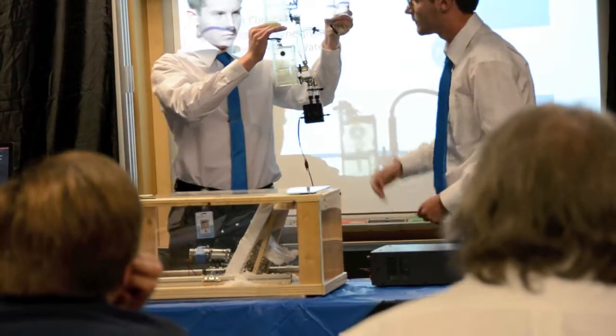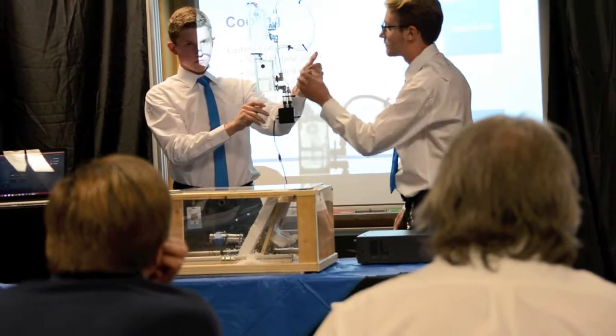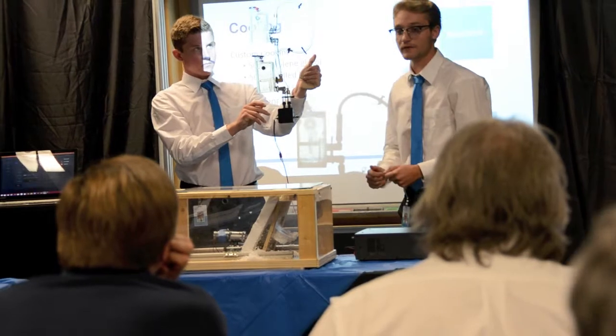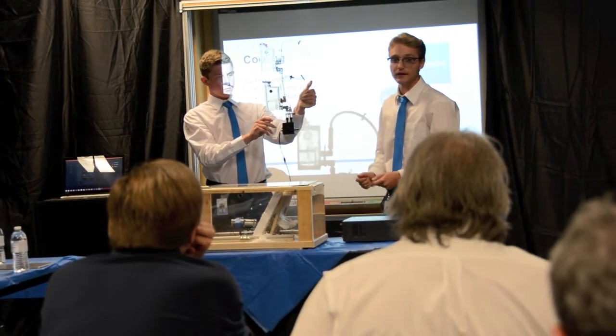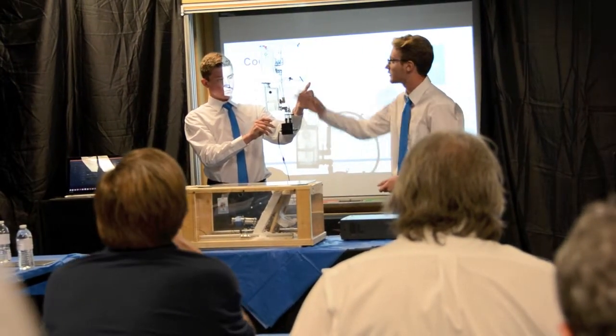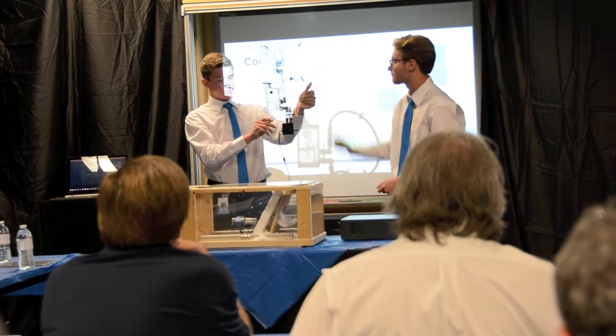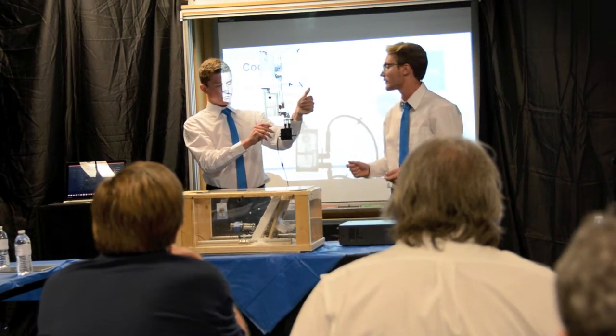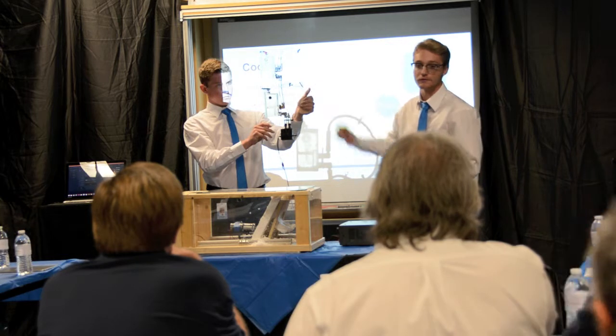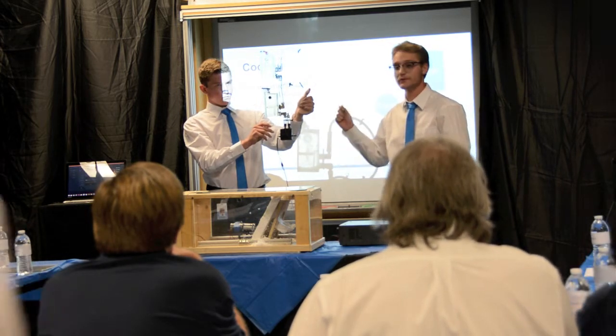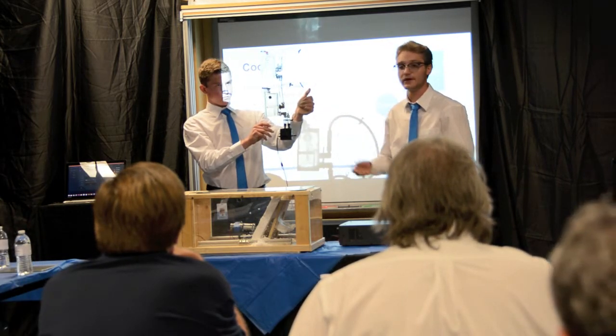Although it may be hard to hear, coolant is flowing throughout the system. Another benefit of using antifreeze is that it doesn't cause corrosion. Additives in the antifreeze prevent any corrosion to the metal fittings used throughout the system. We had this set up for about a month now, and it doesn't show any signs of wear or corrosion. These tests need to be performed in order to show how the system might react in different environments.